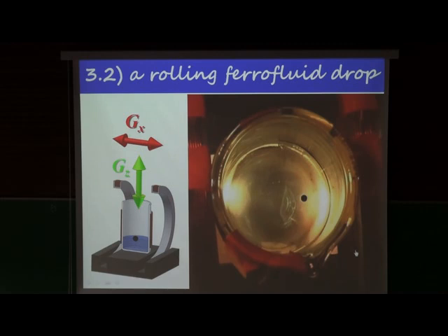So I thought, well, can we do another experiment where it's much easier to measure the flow velocity, where you don't have to immerse these particles, and also where the demagnetization factor is almost the same, notwithstanding the direction of the field. In the channel you have this rotating field, and if the field is in line with the channel, you have another demagnetization factor than if it is orthogonal to the channel. And this makes the comparison of experiment and theory a bit cumbersome.